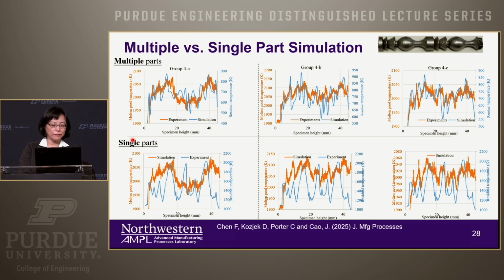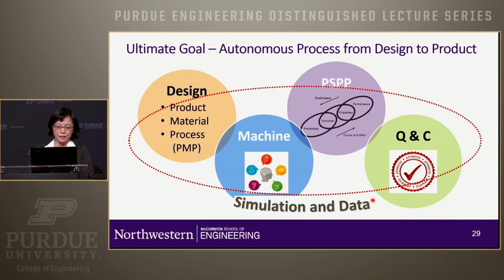Now, very quickly, I mentioned the photodiode system. This is a sanity check, not quantitative but qualitative. If you have multiple parts simulated at the same time, the orange line is our experiment using the photodiode, and the blue line is the simulation. You can see that in general, qualitatively, they match much more closely compared to just a single part. So this gives you a very quick way of checking your temperature profile.